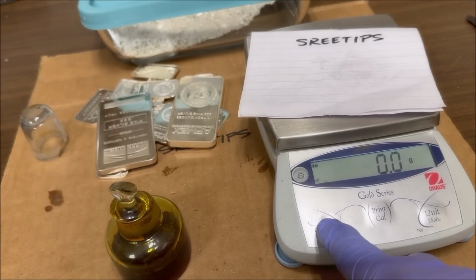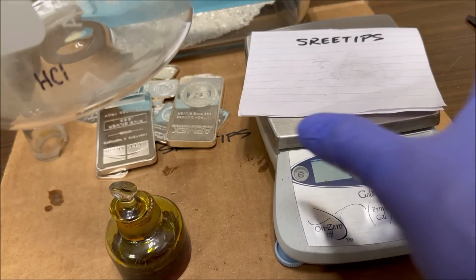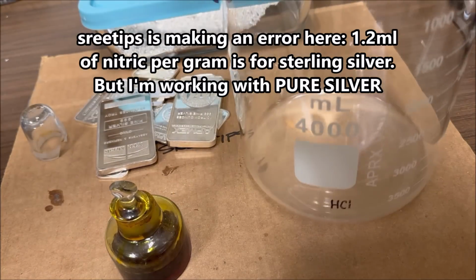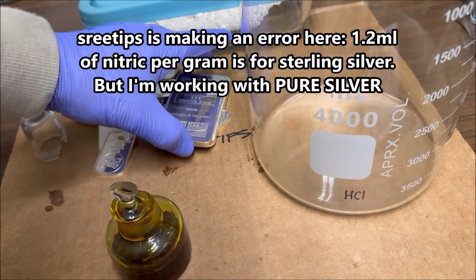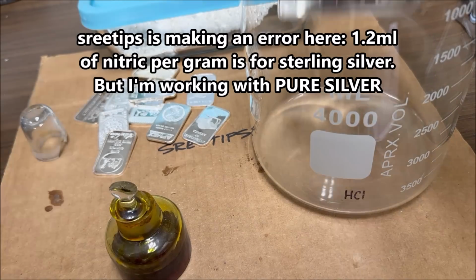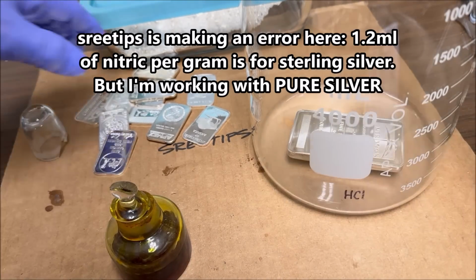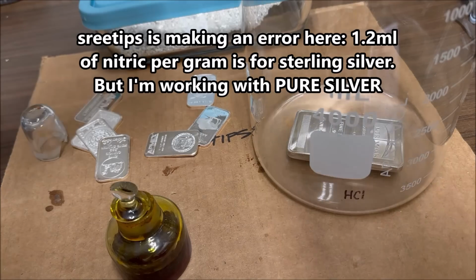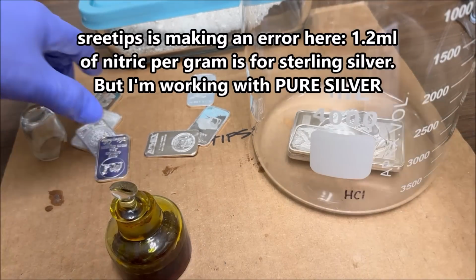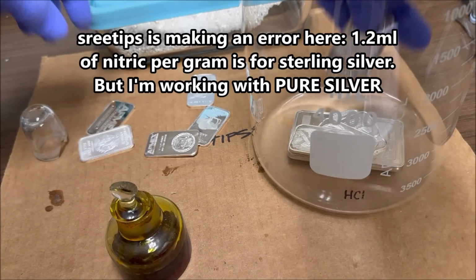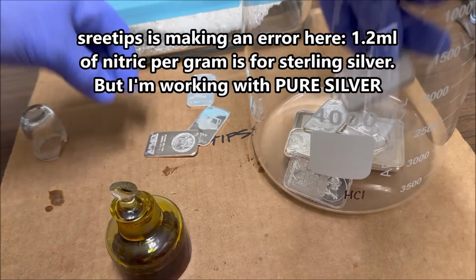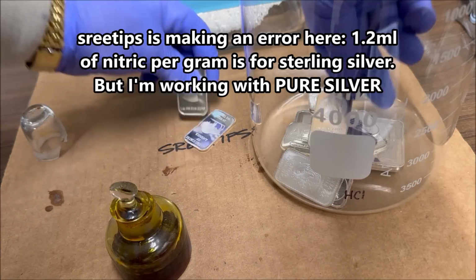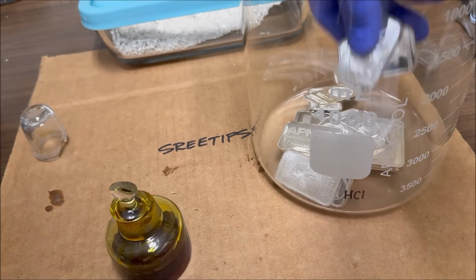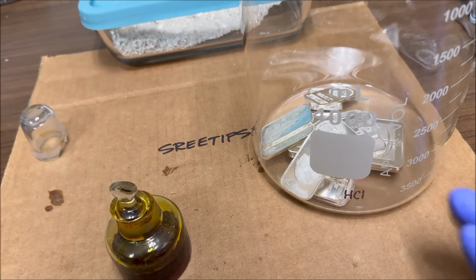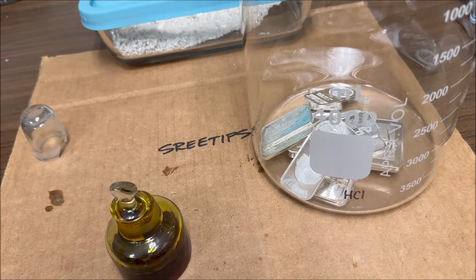Now what we'll do is transfer the silver into a beaker. I need a big one because it takes about 1.2 milliliters of 70% nitric acid and 1.2 milliliters of distilled water. So for that amount of silver, I'm going to need about 2 liters of liquid.